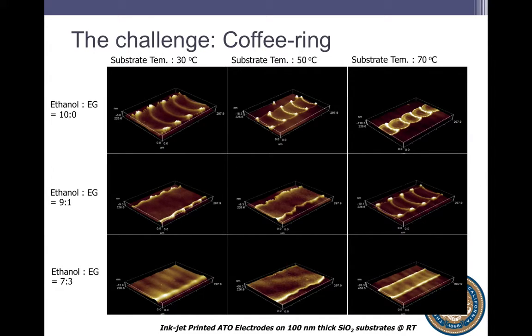And printing of sol gels is tricky because there's an effect that some of you are probably aware of called the coffee ring effect, which as droplets dry causes them to form ridges. And sol gels are really problematic with respect to coffee ring because as they dry, the sol gel gels and it sort of freezes that ridge into the form, and so it's really hard to get uniform thin films. So we've had to do a lot of tricks to get this to work.